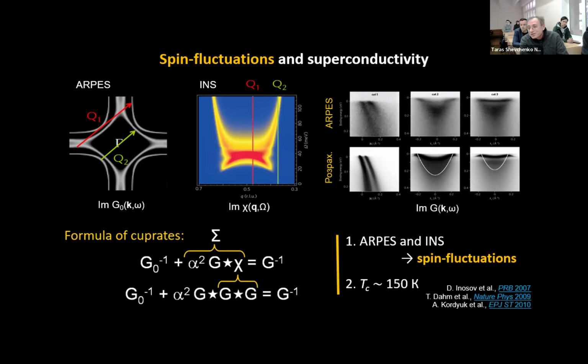This slide represents our result, but not only ours, obtained more than 20 years after the discovery of superconductivity. It is quite an old result already. I want to stress it here because it is a good example of a combination of two experiments. It is a synchrotron experiment, photoemission spectroscopy, and here is the Fermi surface of cuprates measured by angle-resolved photoemission spectroscopy, in combination with a neutron experiment. And this is the so-called two-particle spectrum, the spectrum of spin excitations measured by inelastic neutron scattering.